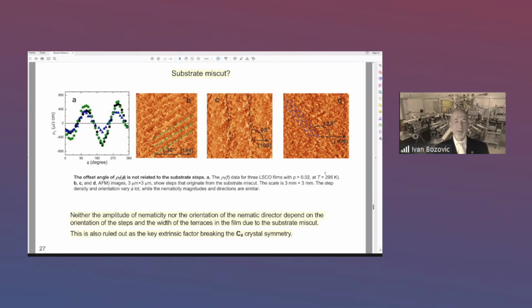To check whether this could be the explanation of the transport anisotropy we observed, we studied films of the same composition, like optimally doped, on substrates with different miscuts. We measure every substrate before the film growth by AFM, atomic force microscopy, and we determine the orientation of the steps. Then we grow the film, then we do AFM again, and we compare them, and lo and behold, the steps in the film are the same as the steps in the substrate.